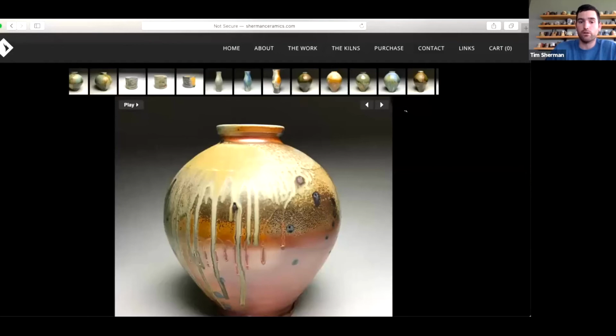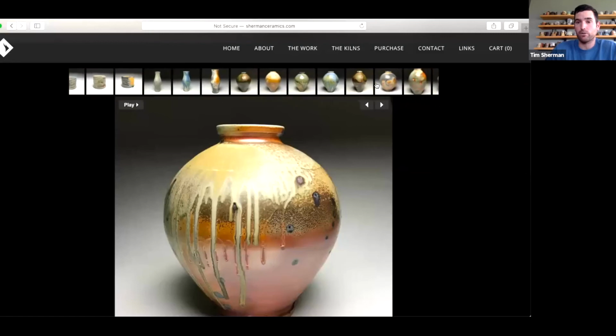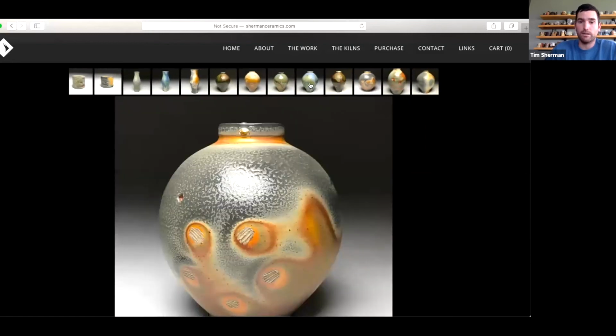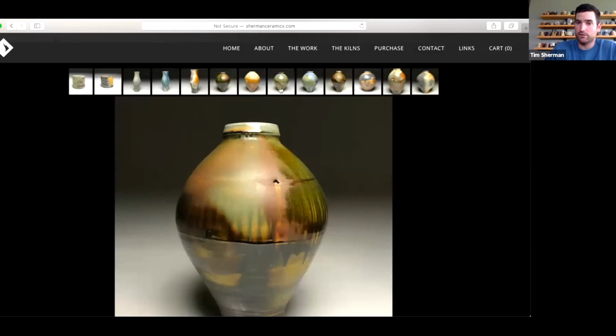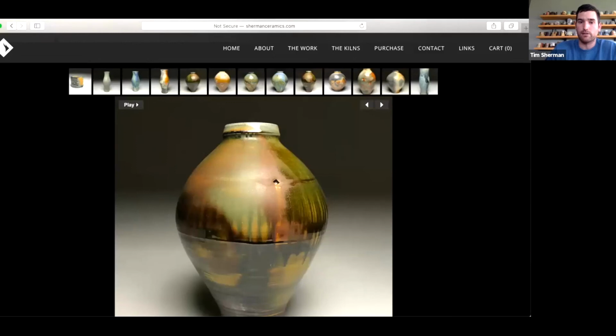Generally, we'll soak the front of the big kiln for 12 to 18 hours, and that's enough time to get every bit of ash on the shoulders and things like that to keep everything melted down so that there's no crusty surfaces. And if you don't do that, I fire where there is plenty of little crusty patches or melon skin. I'm sure some people know or have seen that. And that is just not desirable to me at all. I want everything to be relatively smooth for where it is and what it is.